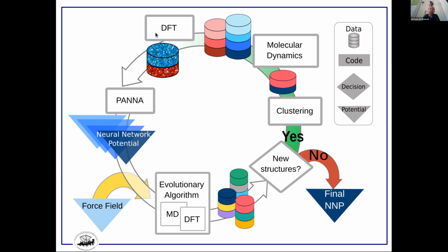And on this set of configurations, you calculate an accurate energy. You do it by DFT. This is the expensive part. So all the initial part is not really expensive because it's all done with a model potential, with some molecular dynamics, but it's not very expensive. The expensive calculations are when you pick a set of configurations and you calculate the DFT. Then you train on this data and therefore, after the training, you have a new neural network potential. And with this neural network potential, you repeat the cycle.